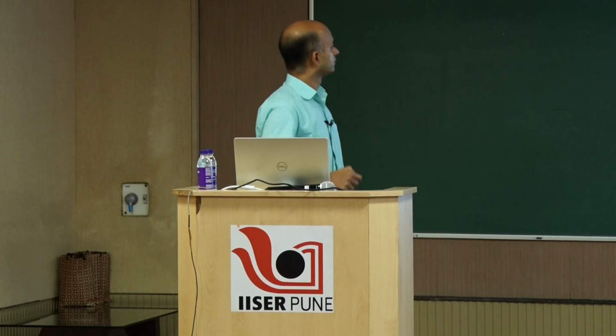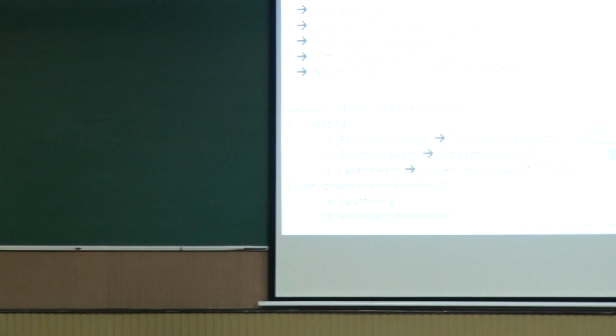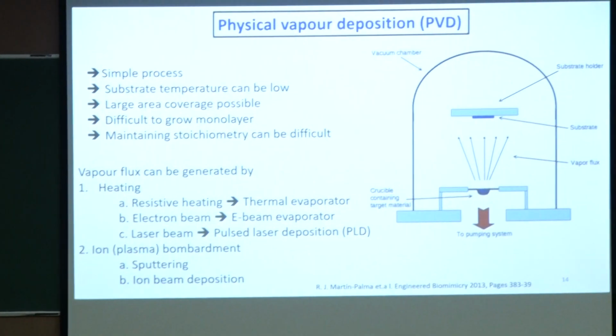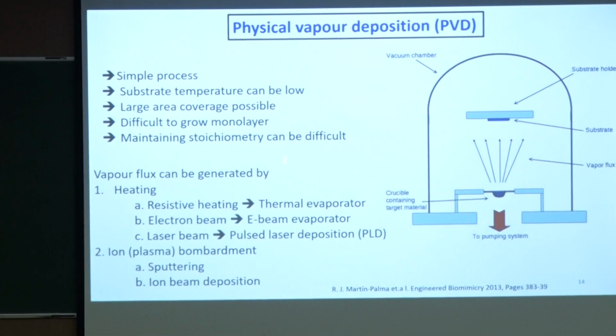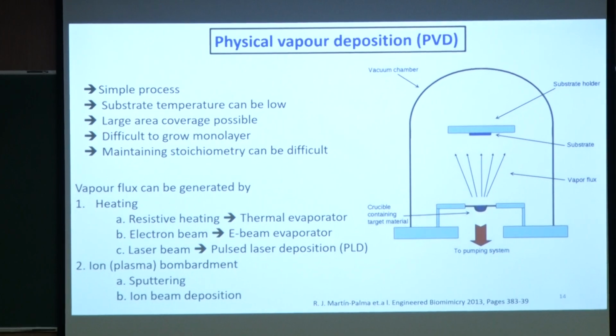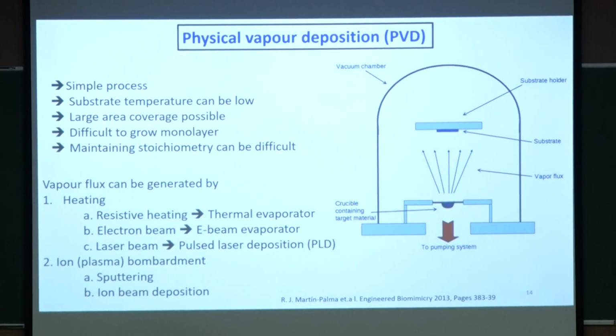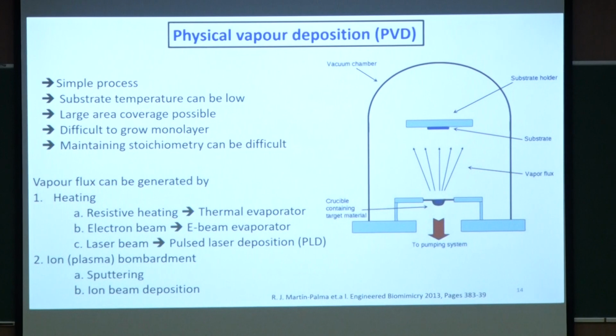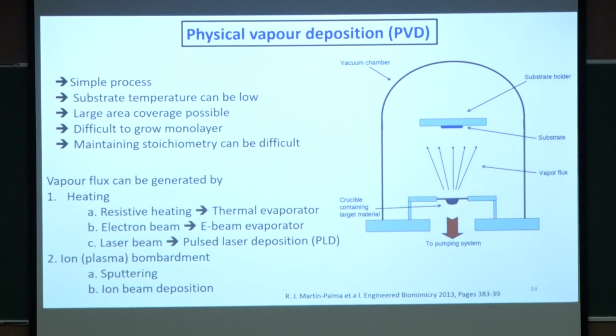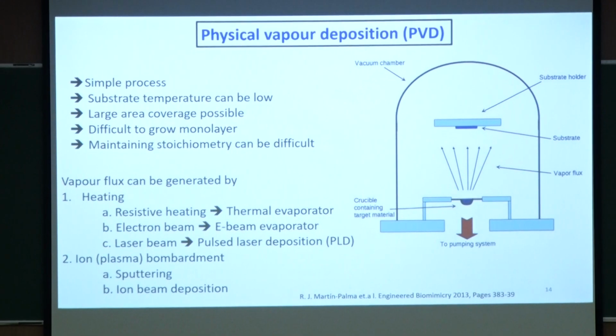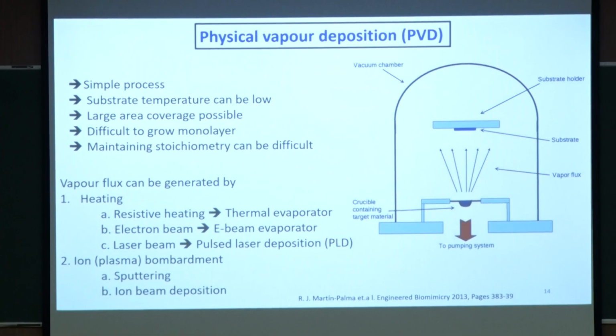So, the next way after exfoliation is physical vapor deposition. The great advantage is that it's a pretty simple process, and you can keep your substrate at room temperature, or even cool it. So, substrate temperature can be pretty low. You can use any kind of substrate, even a heat sensitive, temperature sensitive substrate. You can also use a flexible substrate to coat this. It's very easy to coat them over a large area.